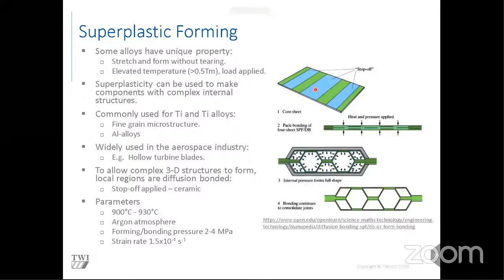And what the stop-off does is prevent a diffusion bond. So when you put the layer on top of this, it will only bond in the green regions, and the blue regions are not bonded. You then apply an internal pressure of hot gas, and that will blow up this structure into a 3D shape.